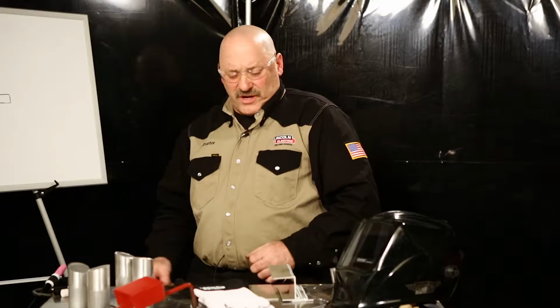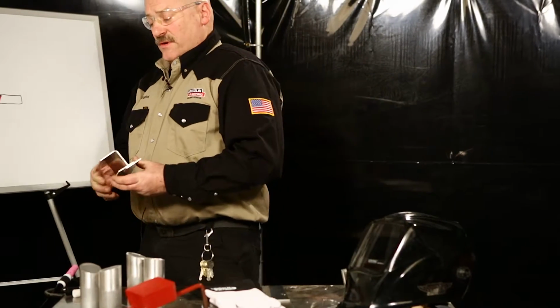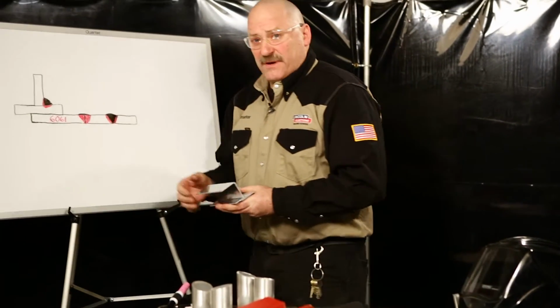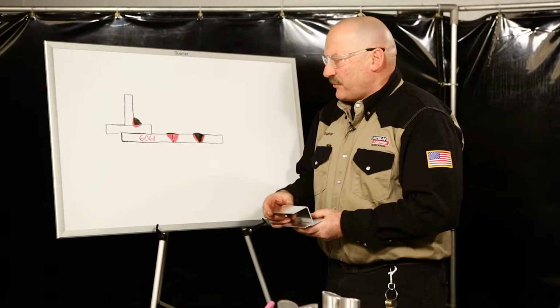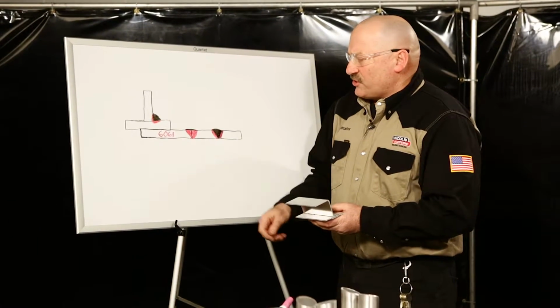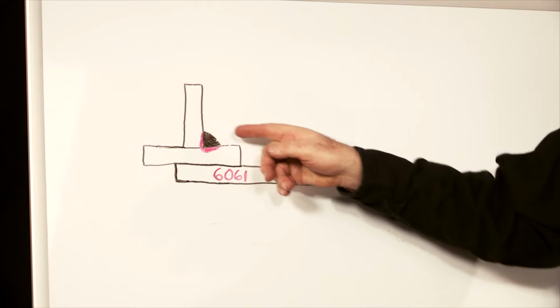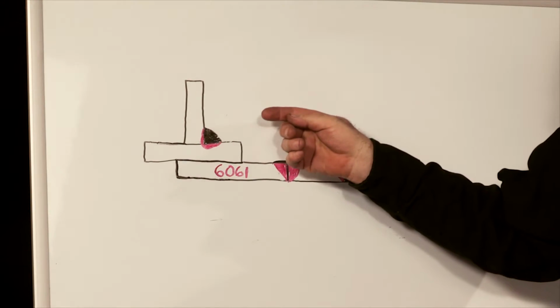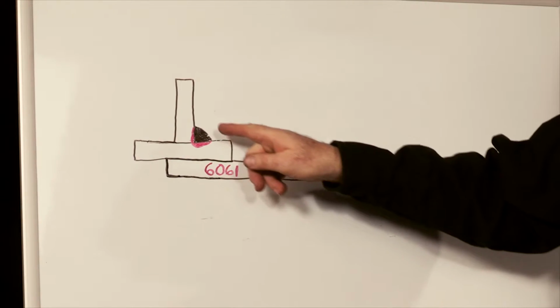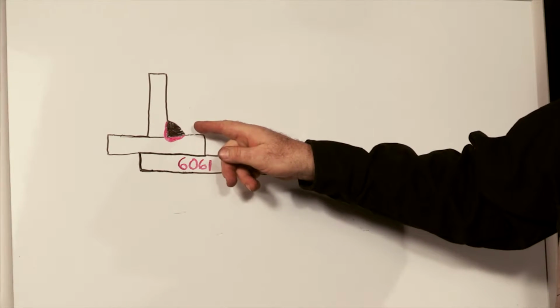Okay, I'm going to use an illustration on the board here to try and show you how these cracks happen and how we can possibly prevent the cracks on 6 series aluminum. Here's a typical T joint. And when we weld a T-joint like this, in order to get adequate strength to the weld, we add filler metal. And if you look, this black area here would be all the filler metal that we added.